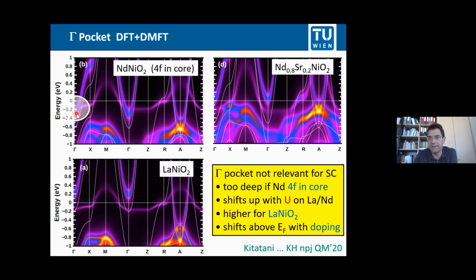It's maybe a little bit too low here in the calculation because for the neodymium, you also have the 4F states that are close to the Fermi level. We know that is wrong. They Hubbard split into Hubbard bands, and therefore you have to deal with them in DFT plus U or put them in the core. And here they have been put in the core, but then your gamma pocket shifts a little bit too low. So if you have a better treatment of the 4F, it's a little bit higher. But anyhow, as you see here, it doesn't matter. Even if you have them too low to start with, if you dope the system into the superconducting doping regime, they are above the Fermi energy. So for the superconducting doping regime, the gamma pocket is not important. And also for the lanthanum nickelate, it shouldn't be there. Okay, that is the gamma pocket.